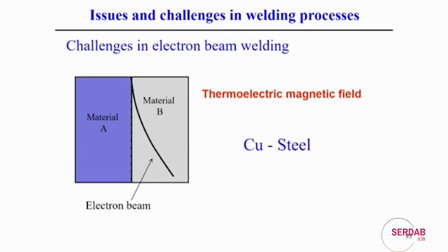But one main challenge of the electron beam welding process arises when you try to join two dissimilar materials. Because the electron beam is a flow of electrons with a defined path, there may be a thermoelectric magnetic field effect, which is better explained by the Seebeck effect. Because of that, the path of the electron beam gets deflected to one side depending upon the magnetic permeability of both materials. For example, with a combination of copper and steel, in most cases the beam is deflected towards the steel. So it is very difficult to focus exactly at the joint interface with such material combinations. That is one of the challenges in electron beam welding.